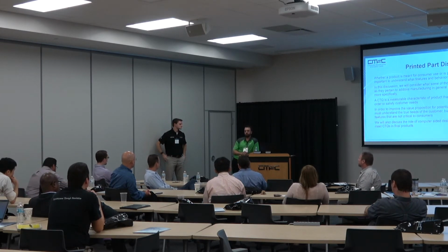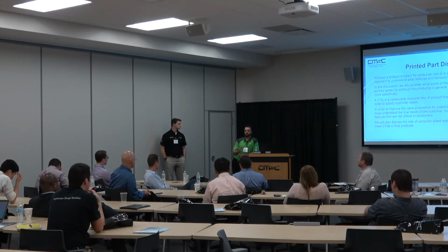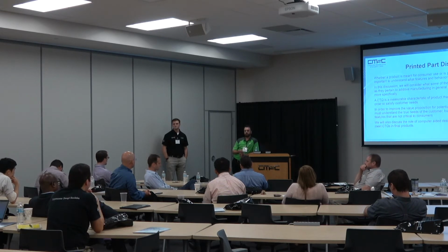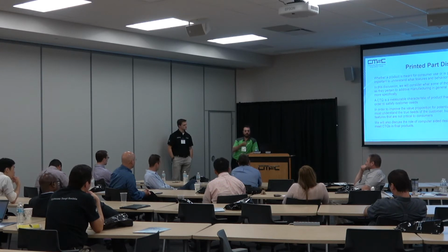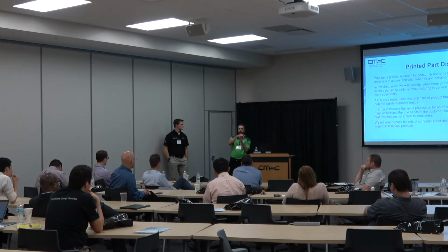We print anywhere from a 0.3-inch wide to a 1-inch wide bead, 100 thou thick to a 1/4-inch thick bead. So high fidelity in details is not easy. Typically, on the machine side, we try to machine the detail in there. But even still, we try not to machine past a one-bead wall. Because we talked about bead-to-bead compaction: if you machine down through the first bead, you'll start going into the second bead, and in between the two is where you'll find porosity.